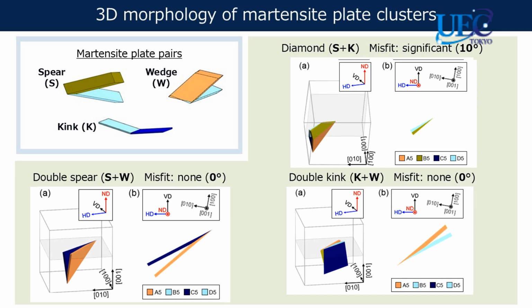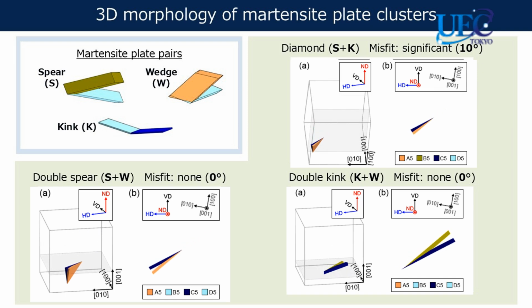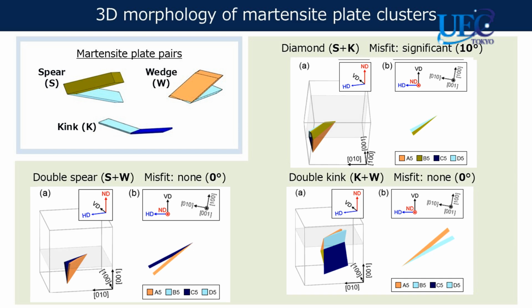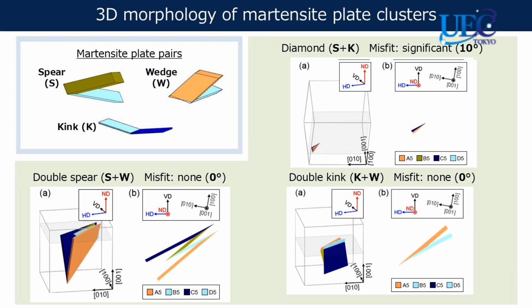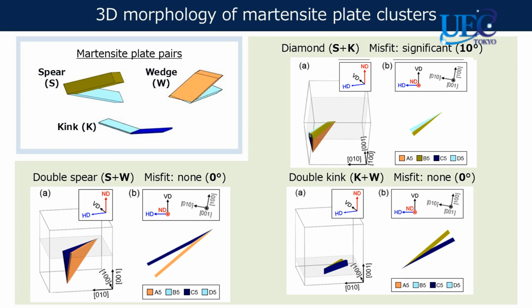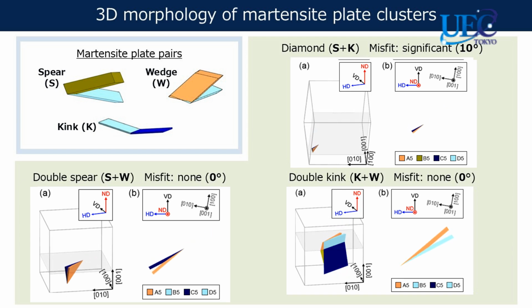Kinematic theory shows that misfit is introduced when the diamond cluster forms, while misfit is cancelled for the other two clusters. In other words, the diamond cluster accumulates the misfit of spear and kink. Misfit accumulation in the diamond cluster is considered unfavorable for formation. Microstructure observations show that the diamond cluster formation was suppressed. This result allows us to discuss cluster formation from the perspective of misfit.